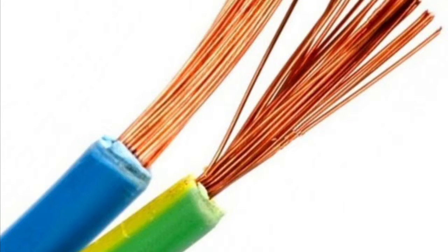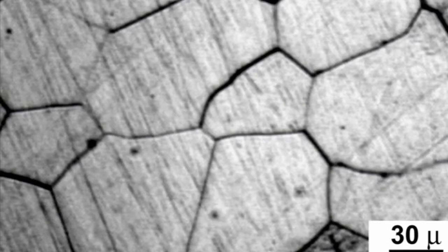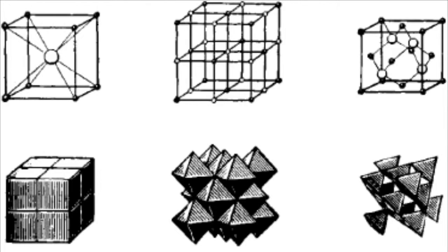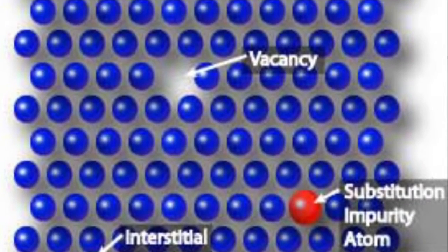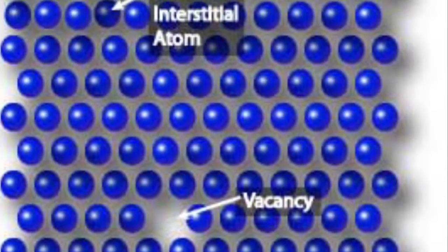So, I'm going to describe the microstructure of the copper wire. Most copper wire is produced using a drawing process in which plastic deformation leads to changes in grain size and crystallographic texture. During the first stage of the deformation, the grains are divided, change shape, and also elongate in the direction of the stress. It also creates a large amount of point defects.